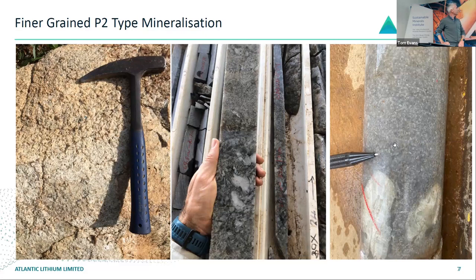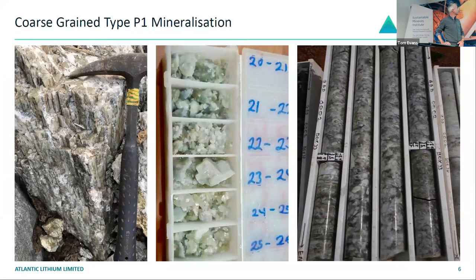So the grade of this material here is also around 1.2 up to 2% lithium oxide, as is the grade in this material. So this would probably be high grade, at around 2% lithium oxide. And then once it's concentrated, you'll get to that 6% concentrate value. It's amazing to see how that grain size varies. These are all just very fine spodumene crystals, and it gives that same overall resource grade of 1.25.